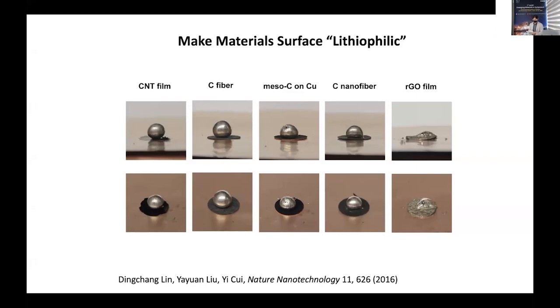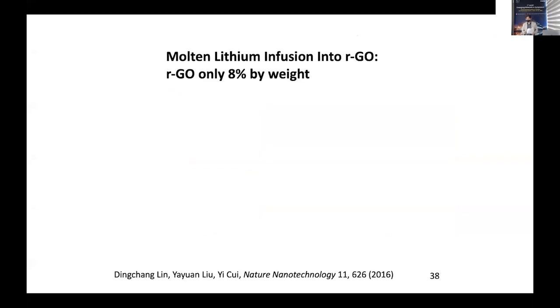And the gap between the graphene oxide is a capillary, there's a capillary force interaction right there, pulling molten lithium into the graphene oxide. And indeed, we don't have to use a heavy weight of graphene oxide. It's only 8% by weight. So you don't reduce the lithium metal's high capacity that much. It's still very, very high.